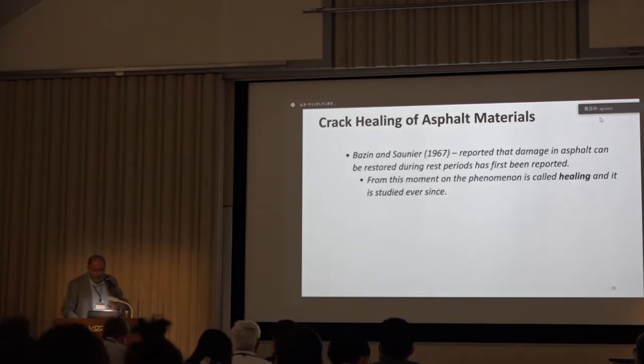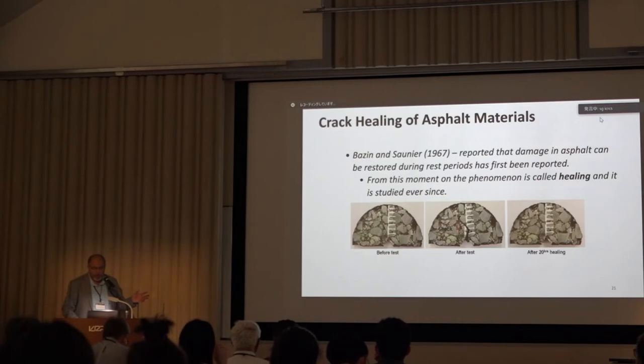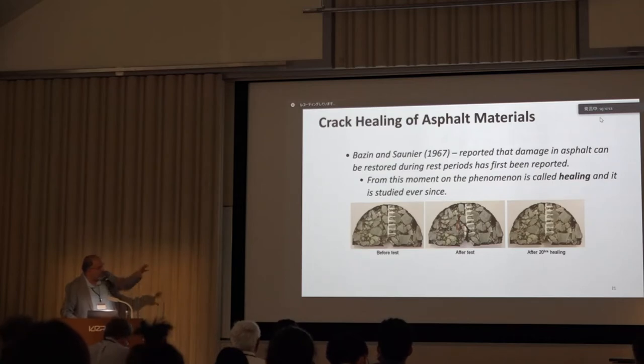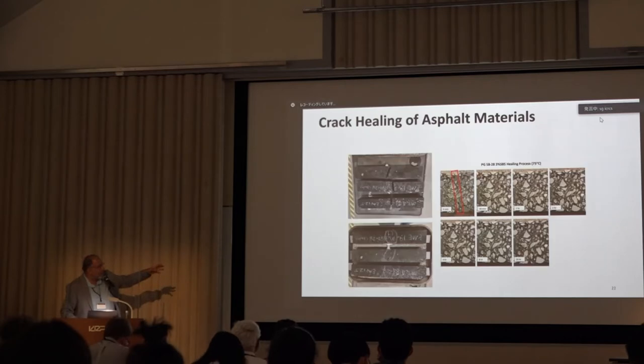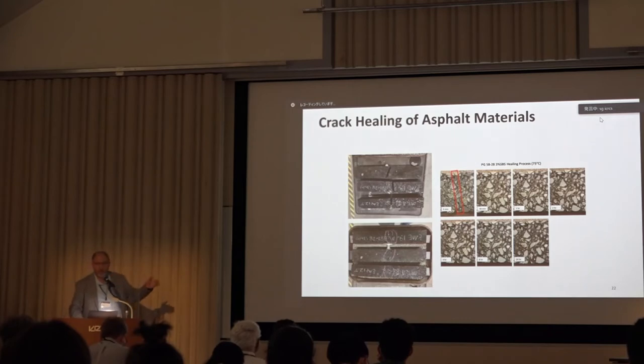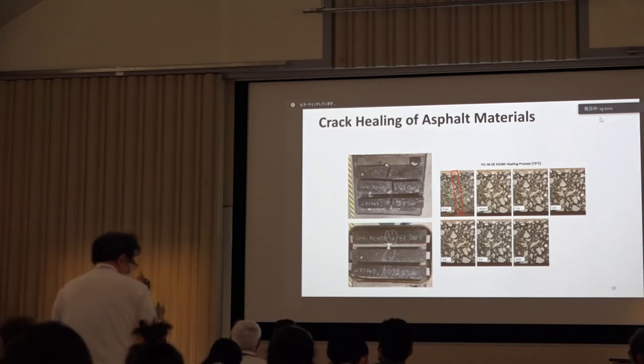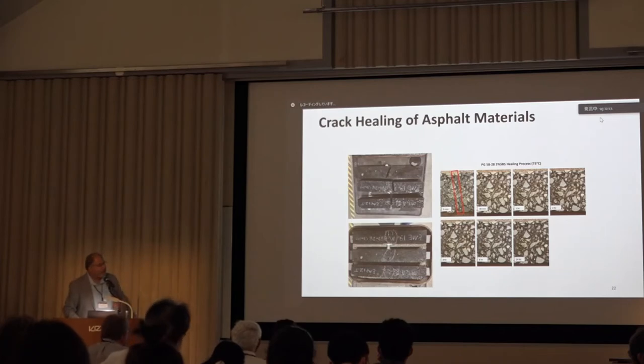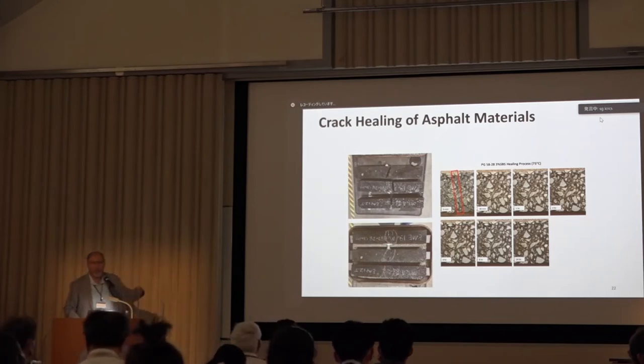Okay, so the early research on asphalt cracking started in the 60s of the 20th century, and these are some old pictures actually showing that the cracks will heal. We did similar things in our lab when we hosted cluster F. Cluster F is the last cluster in the list of the RILEM clusters. I hosted the meeting in 2019, and my students present in the room, like Rob and Dandy, did this in the lab. They broke the sample, put it back in the oven at certain temperature, and we demonstrated that healing happened.